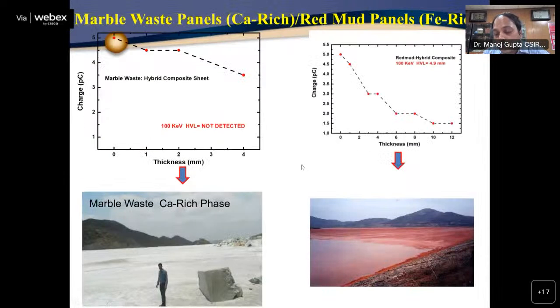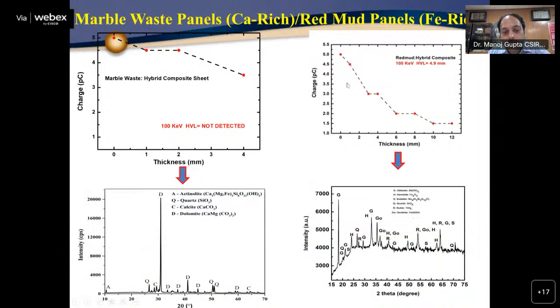Now, to validate whether the iron oxide or titanium oxide has such capability to protect against X-rays, we fabricated two panels, one with marble waste, which has calcium rich phases, and one with iron rich phases. In the case of the marble waste panels, we don't get any HVL, meaning very little energy is dissipated. But in the case of the red mud, the energy is absorbed. This is the main reason: the iron. Now if we compare the X-ray diffraction patterns of the marble as well as red mud, in the case of marble waste it has the dolomite or calcite phase, which does not have the capability to absorb X-rays. But here we can clearly see the difference.